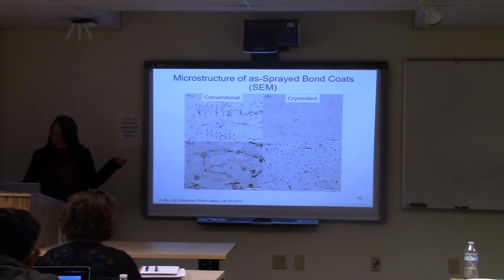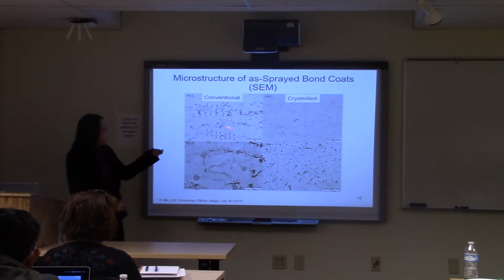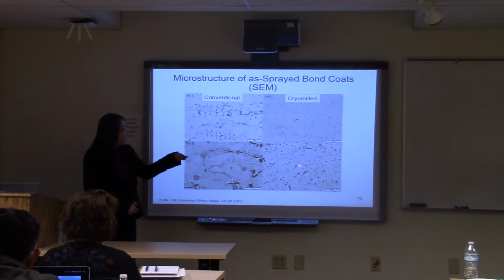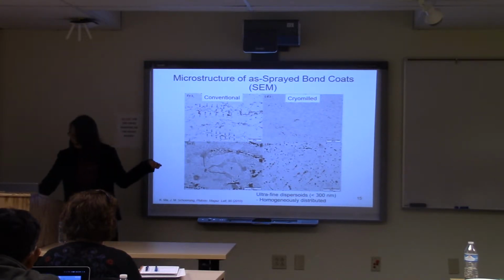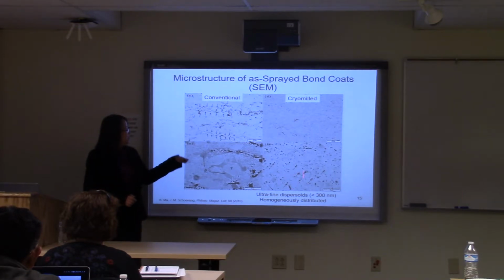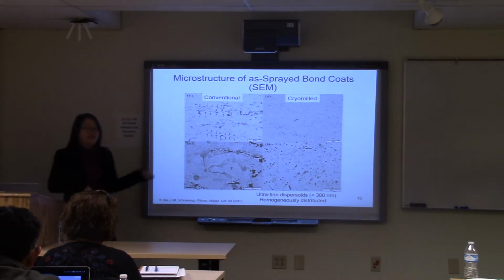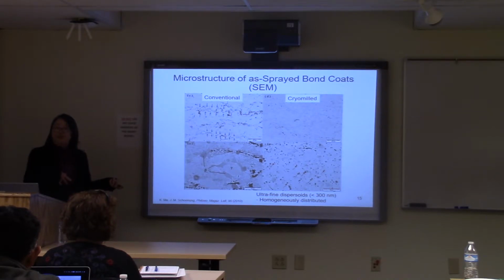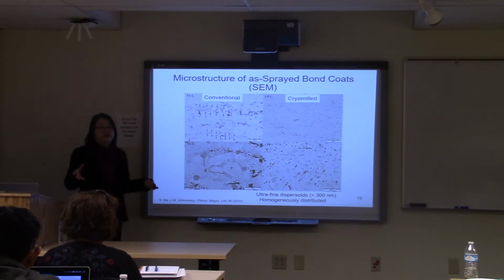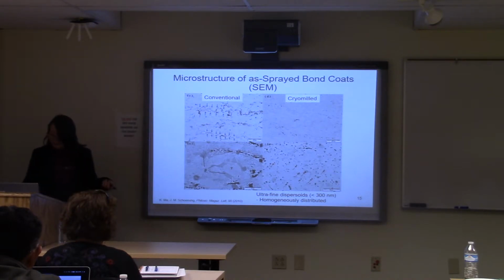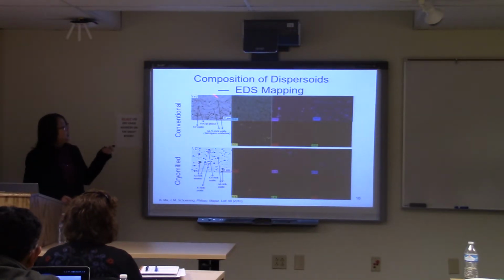However, in the cryomilled material, we don't see this anymore. We still see very small dispersoids, below about 300 nanometers, very well distributed in here. And if you recall the TEM results of the powder, I already showed those oxides and nitrides already exist in the powder. By doing the EDS mapping, we tried to further identify the chemical composition of those, and we find, in addition to the aluminum yttrium-rich oxide, aluminum-rich nitride in this system.